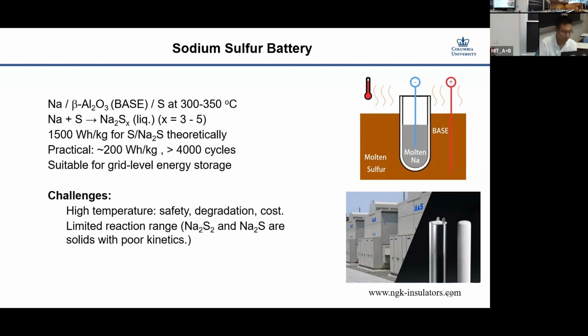On the other side, the major challenges are the high temperature, which not only causes safety concerns, but also sodium metal at such high temperature is very corrosive, so it actually still damages the alumina to some extent each time. Also, as mentioned, we cannot go to sodium disulfide and sodium sulfide because these two phases have bad kinetics at high temperature. Forgot to mention, this system has hundreds of megawatt hours of installation mainly in Japan. So there are some real demonstrations, but the technology still needs to be improved.